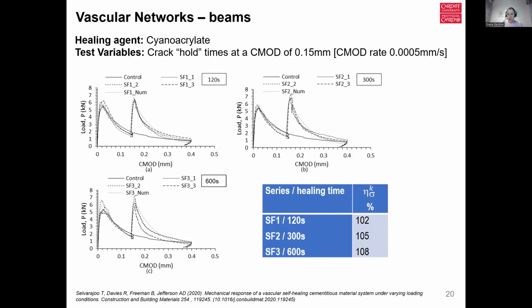The tensile strength of the cured CA is approximately 21 megapascals, which is considerably stronger than the tensile strength of the concrete. And this implies that a specimen will not re-crack directly through the cured healing agent, but rather re-crack directly or adjacent to the healed zone, and so a crack will form around it. However, as pointed out by previous researchers, this interface zone isn't formed of only plain concrete, since the cyanoacrylate actually permeates into the microcrack zone adjacent to the macrocrack and creates a cementitious polymer composite with a high compressive strength.